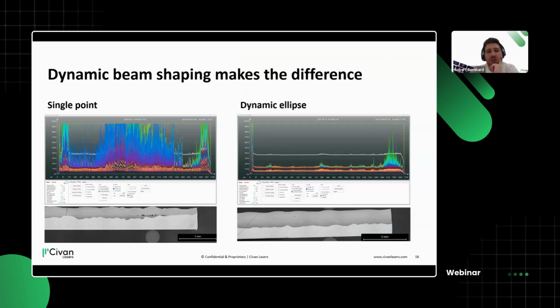Something I also like to show a lot is the difference when you start to measure your laser process. There's pretty nice tech out there. In this case, we used a 4D sensor, but also the Precitec LWM works well. We've proven it, and the Plasmo process observer is also a very good option. What I find interesting, and I think what someone can see, is that, again, talking single point versus our dynamic ellipse, we get cracks during the welding, but also a lot of back scattering, which we attribute to the keyhole collapse that we can see during the welding.